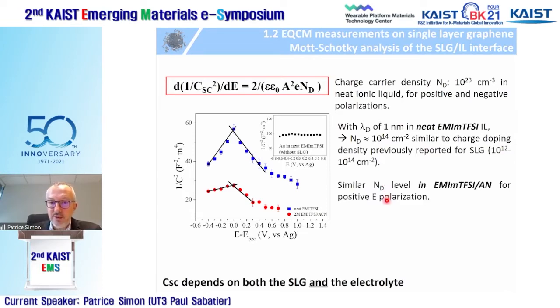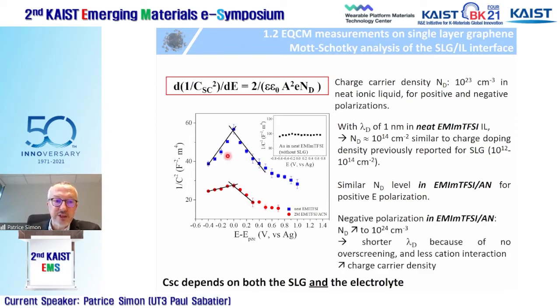And what is interesting is that you have similar doping level, similar charge carrier level on both sides of the plot in EMI-TFSI in acetonitrile, here for the positive polarization. However, if you move to negative polarization here, you can see a big difference between the charge carrier density in solvated and unsolvated electrolyte. And this is explained when you add acetonitrile: you decrease the Debye length because of no overscreening and less cation interactions with the surface of the graphene, and you increase the charge carrier density.